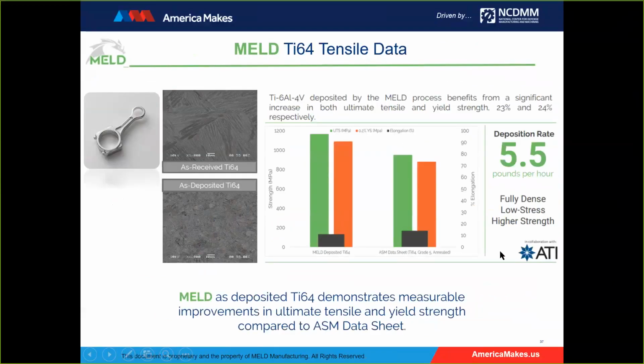We've done work with titanium. You can see MELD as deposited compared to the ASM data sheet. So again, as deposited, we were showing really good mechanical properties compared to the data sheet. We haven't done a lot of titanium work over the last few years. We've done a handful of projects. We've currently achieved a deposition rate of 5.5 pounds per hour. The more we play with the material, the faster the deposition rate as we optimize the parameter settings on our machines for titanium.